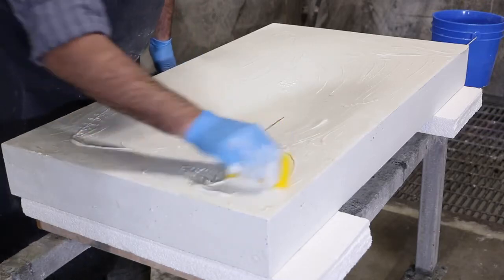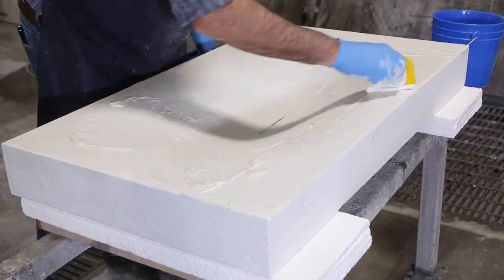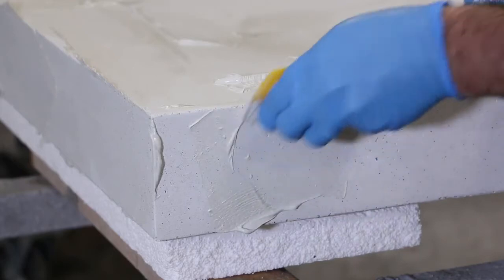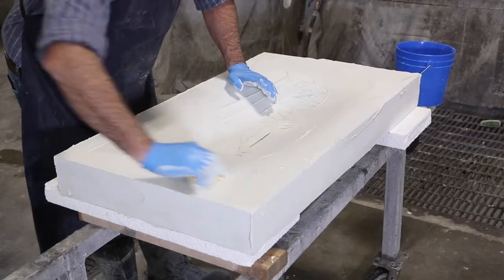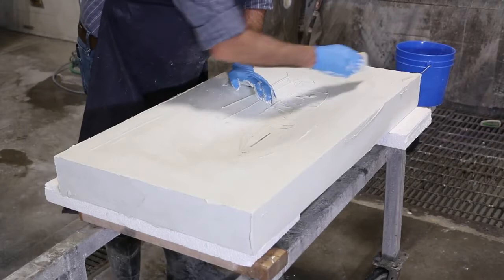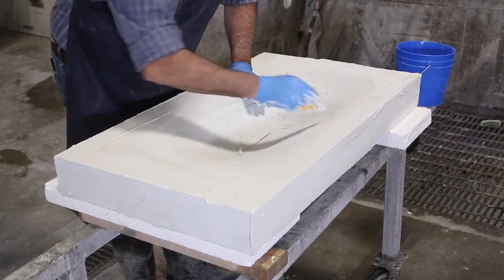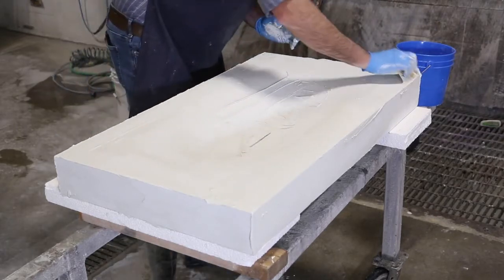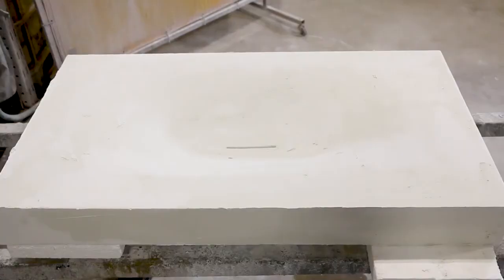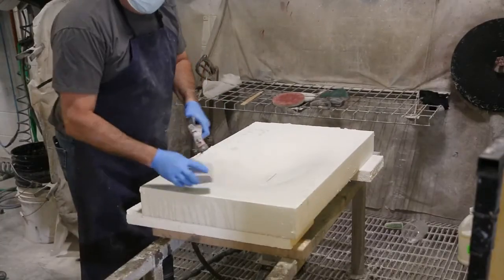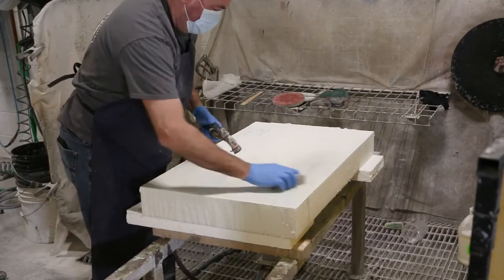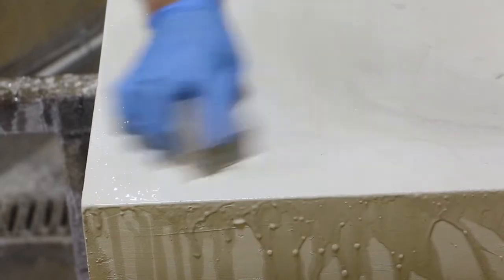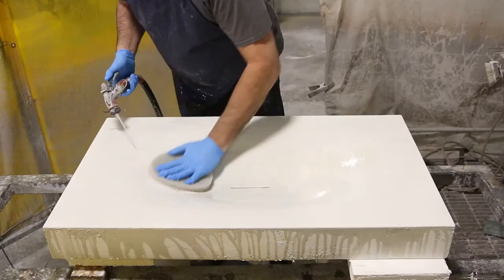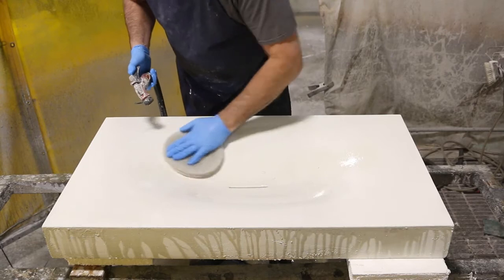Using a soft plastic spreader, I apply over top to a thin uniform thickness, which helps with proper application to all areas. Working in multiple directions helps to work the bone paste into the voids. The bone paste application is complete and allowed to cure overnight. The next day, using a 120 grit diamond hand pad, I removed the excess bone paste by wet sanding. Diamond-coated Spinflex pads work well for the basin.